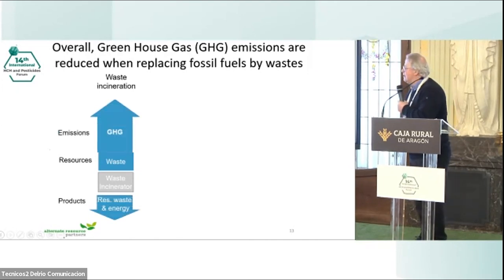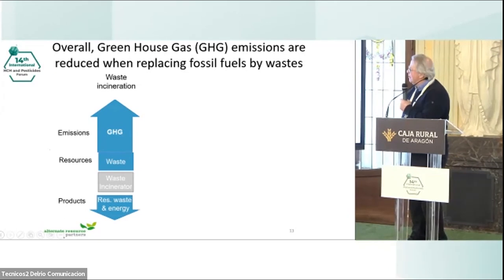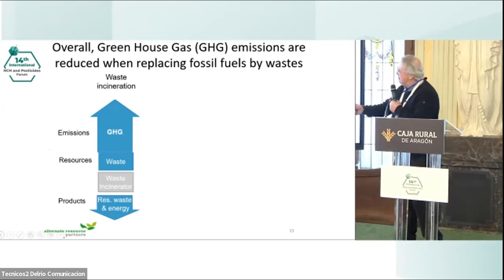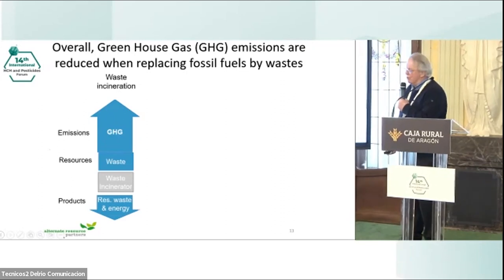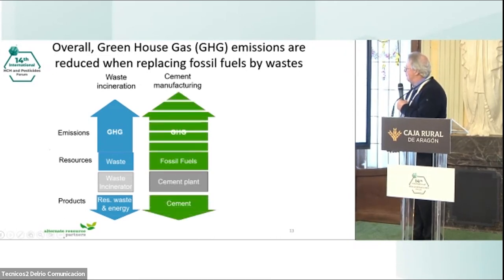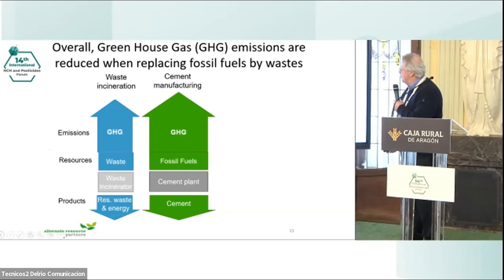Basically, if you look at the waste incinerator, it's using the waste. It will have about 40% going to landfill, and then the greenhouse gases are produced. If you do the same thing, you have the fossil fuels, you have the greenhouse gas from the cement industry, which is much bigger than from a waste incinerator, not only because of the emissions of the fuel, but also from the product, which is CO2, because we need to drive the CO2 off the calcium to get the lime. And we have no landfill, as I said.